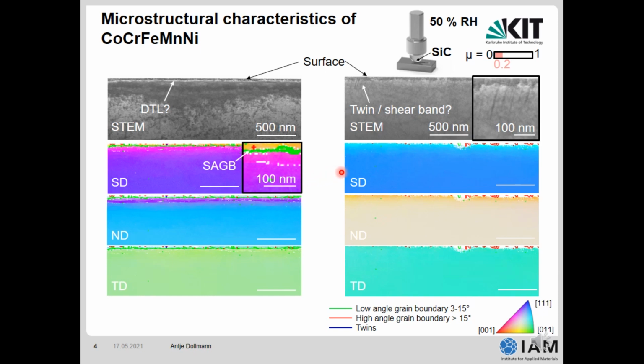And we have also seen before that the dislocation trace line often has a low angle grain boundary character. And here in the second measurement, unfortunately, the resolution of the measurement is too bad, so we cannot say what these bands are.